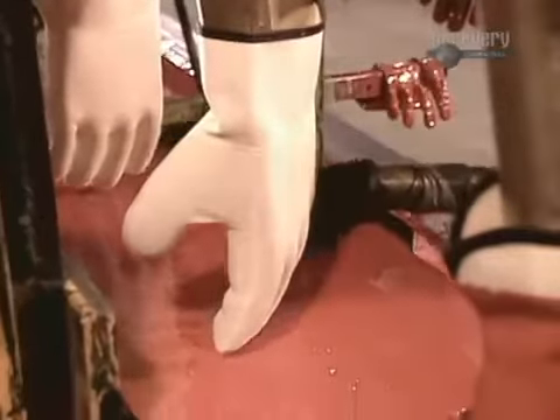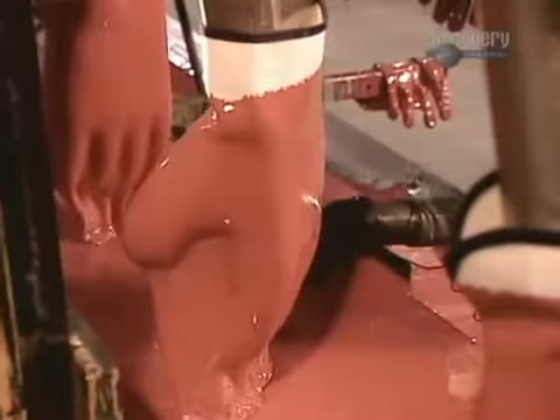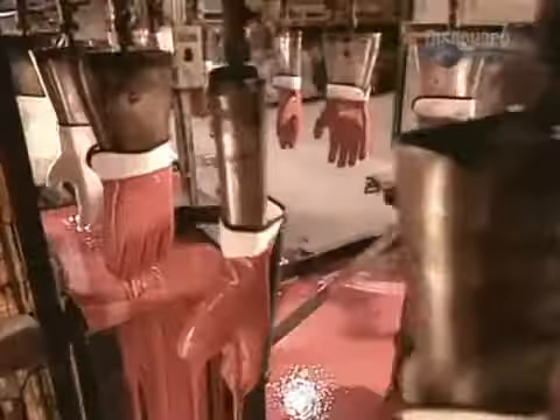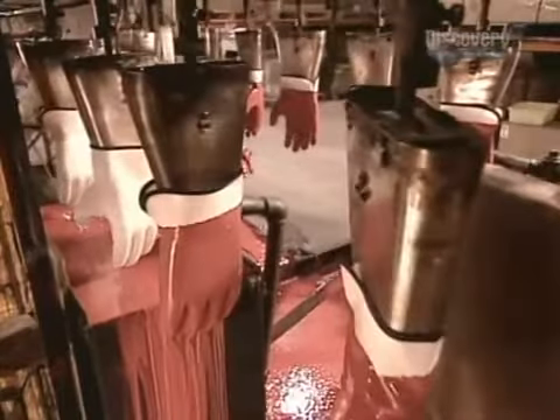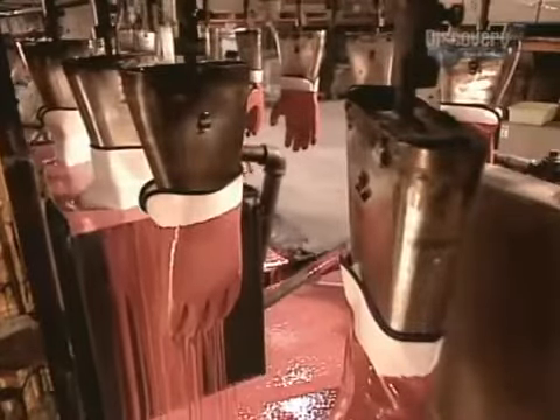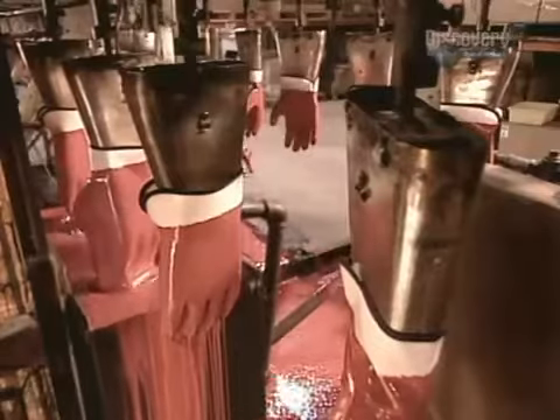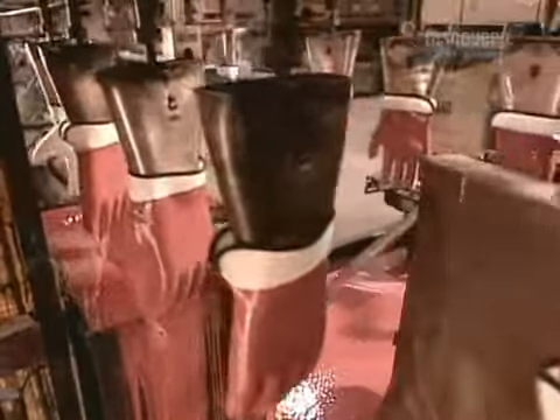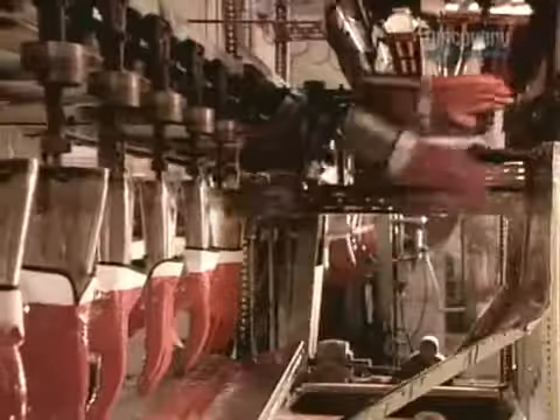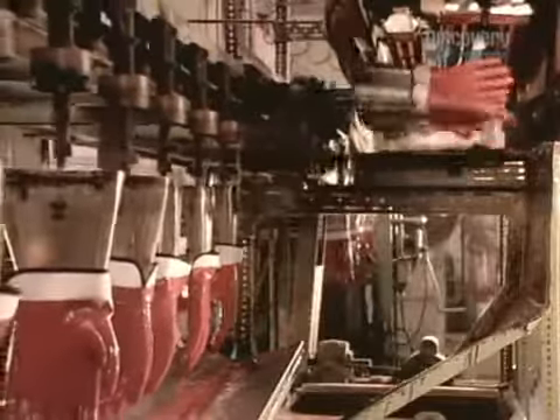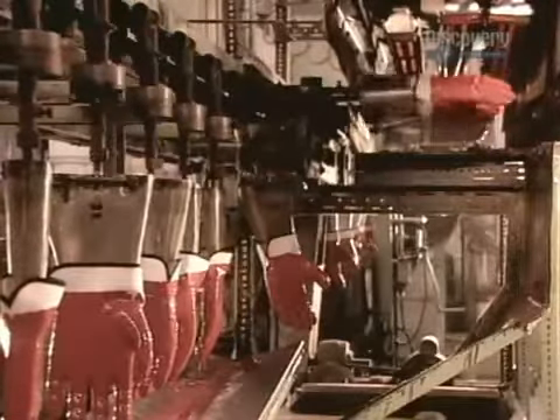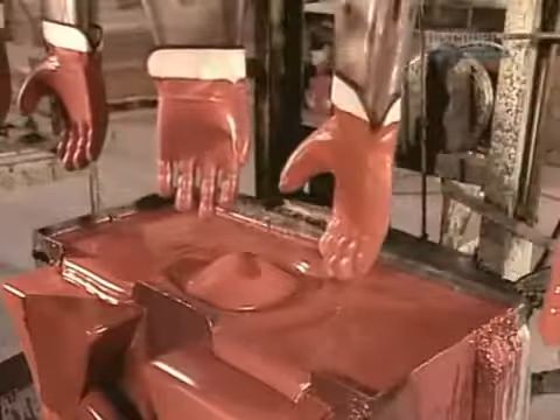Then it's into the PVC bath. The basin of liquid PVC moves upward, coating the liners. As the basin descends, the excess drips off. Then the gloves go for a spin under infrared lamps for about 45 seconds. The spinning spreads the PVC uniformly so that it doesn't accumulate on the tips of the fingers, forming clumps. The heat ensures it dries evenly.